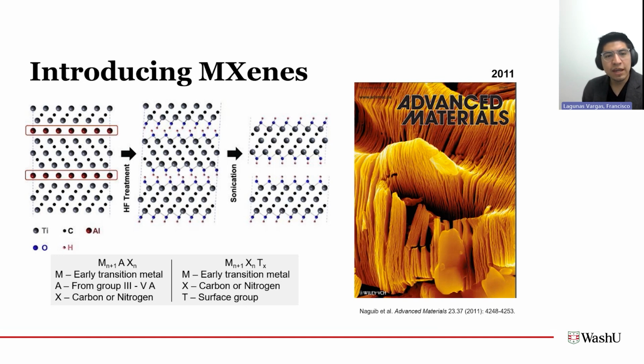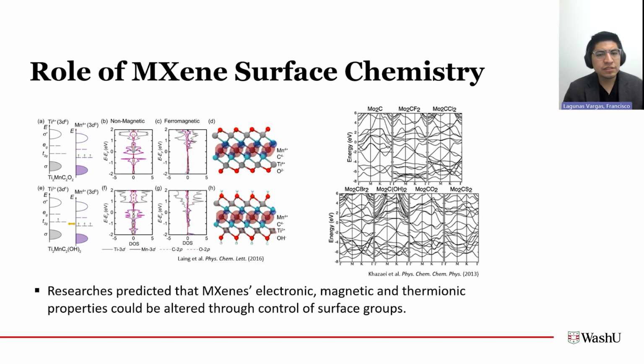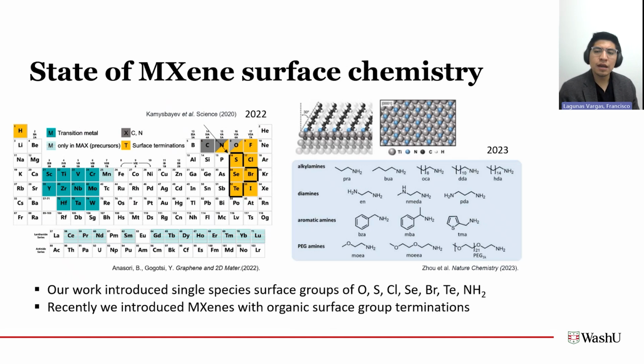So typically, to etch away this aluminum layer, you need to use very strong etchants, such as hydrofluoric acid. And when you use HF, you cover the surface of these new sheets with fluorine, oxygen, and hydroxyl surface groups. Now, there's a lot of interest in being able to move beyond those particular types of surface groups because researchers have shown, or have predicted, that if you can selectively pick different surface terminations, you can actually start introducing some new material properties. So that's kind of where my work came in.